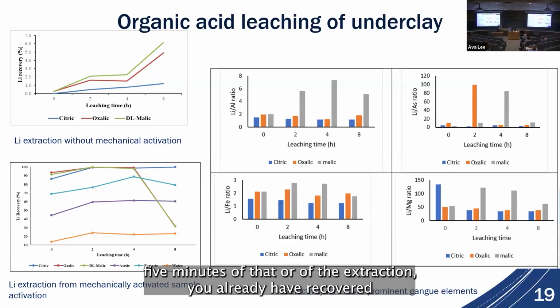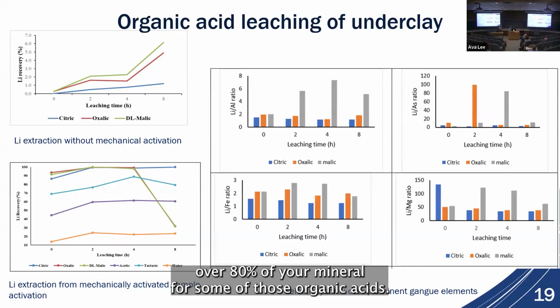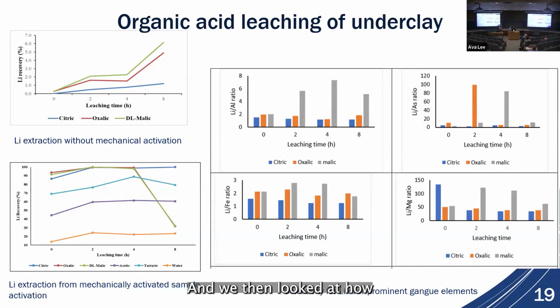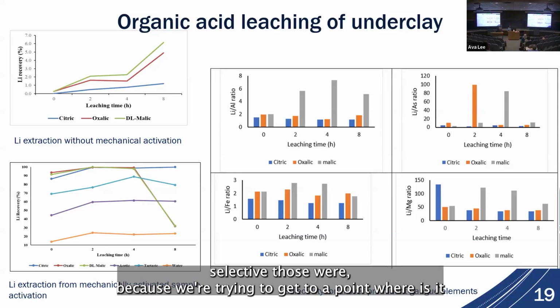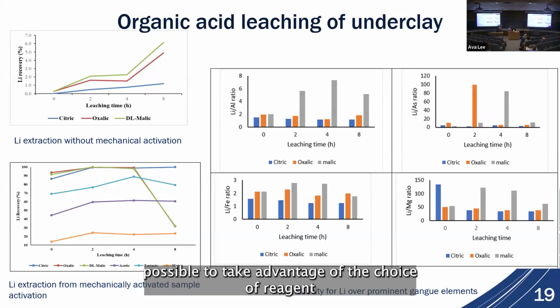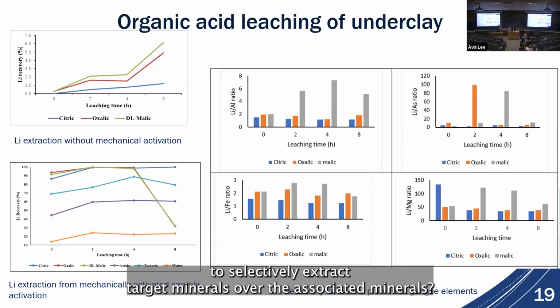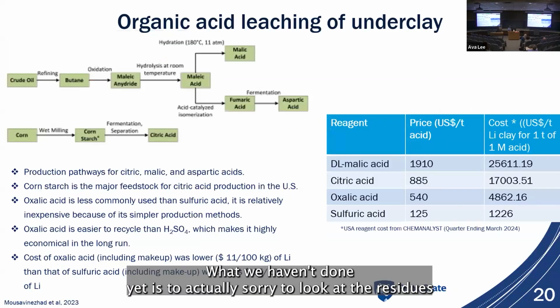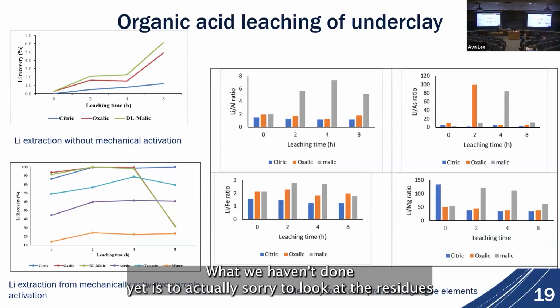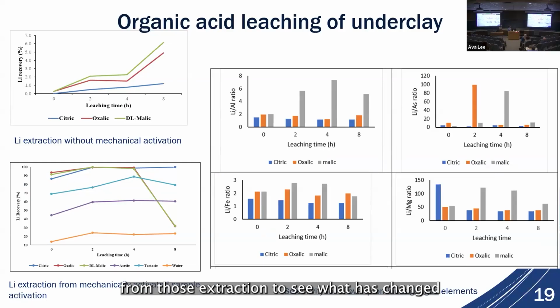Within the first 5 minutes of the extraction, you already have recovered over 80% of your mineral for some of those organic acids. And we then looked at how selective those were, because we're trying to get to a point where is it possible to take advantage of the choice of reagent to selectively extract target minerals over the associated minerals. What we haven't done yet is to actually look at the residues from this extraction to see what has changed in their structure.